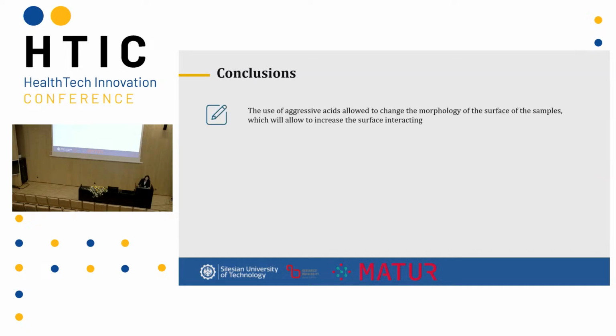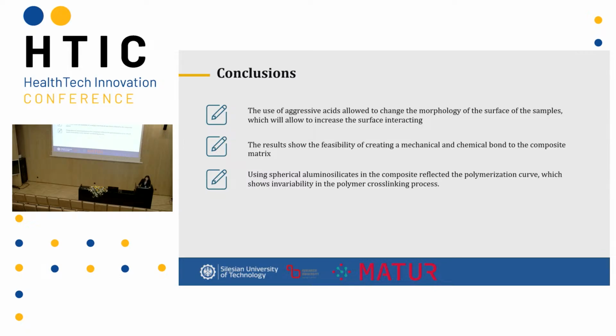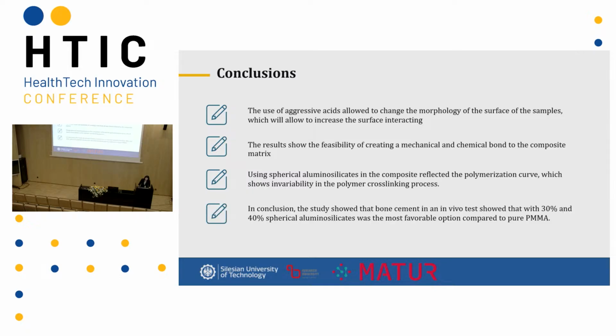To conclude, the use of aggressive acid allows changing the morphology of the surface of the samples, which allows increasing the surface interaction. The results showed the feasibility of creating a mechanical and chemical bond to the composite matrix, and using spherical aluminosilicates in the composite does not alter the polymerization curve, which shows invariability in the polymer's cross-linking process. And the study shows that in bone cement in vitro tests, 30 and 40% spherical aluminosilicates was the most favorable option compared to pure PMMA. So that amount of aluminosilicates is better to use.